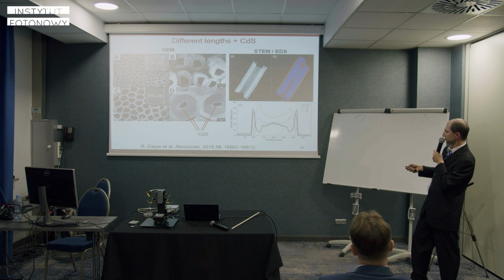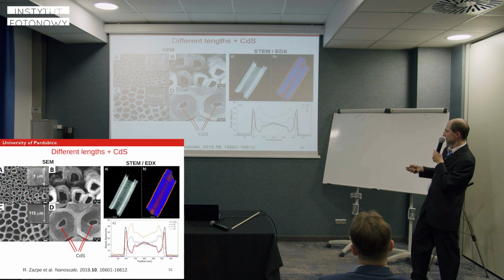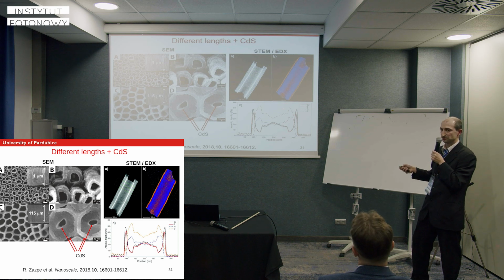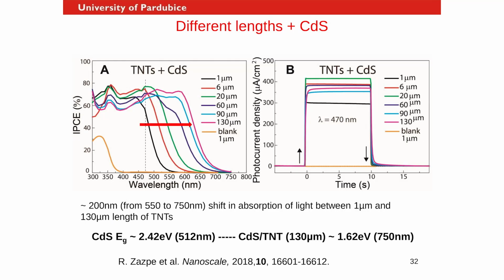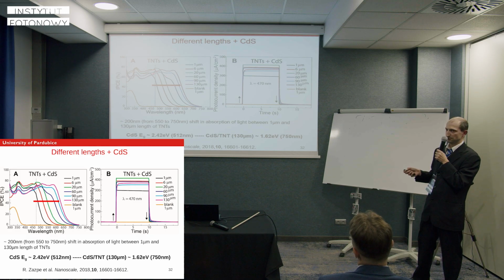Yes, this is a signal. Cadmium is black and sulfur is red. So it's perfectly coated on both edges and also in the interior of the tubes. And here are the results. So this is a reference sample, and then all of them had around 70% of IPCE value.